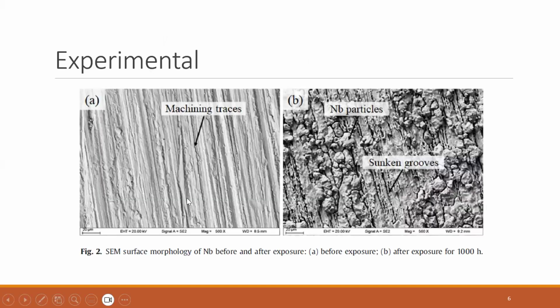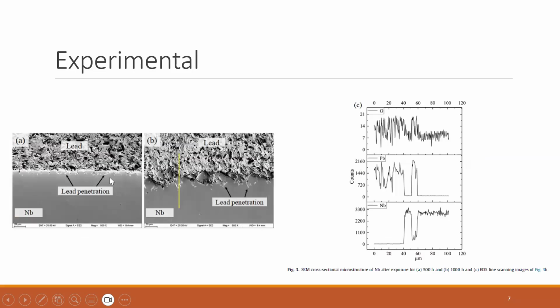And this is figure 2, surface morphology on niobium before and after exposure. This is before exposure, you can see the machining traces, and this is after exposure for 1,000 hours. So this is Nb particles, and these are sunken grooves. And in figure 3, we can see cross-sectional microstructure of niobium after exposure. This is for 500 hours and this for 1,000 hours.